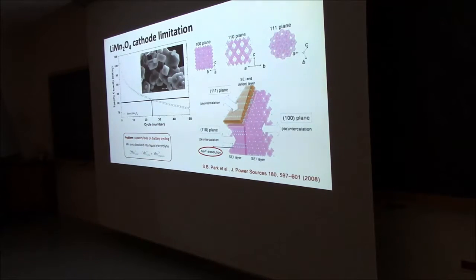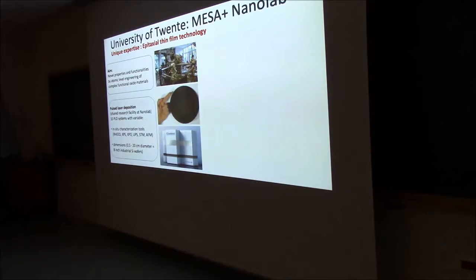Which facet is in contact with your electrolyte, and that will stimulate this dissolution. But if they normally make materials, they make all these powders, all the facets are available, or many are available. This is not very well controlled. So this was our starting point to say, okay, let's see if we can do that. If we make thin films where we control the specific orientation towards the liquid.